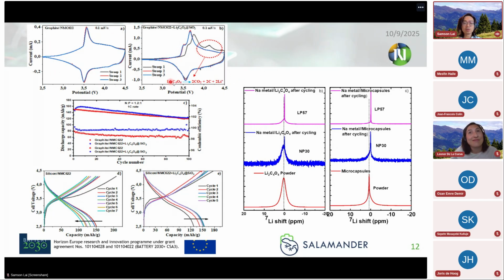And so when you look at the discharge capacity over time, you see that it's much more stable and much better retention over 100 cycles. And we're also really able to confirm that there is lithium oxalate inside these things because we were able to do in situ NMR. And here we did it actually in a sodium metal system so that you didn't get confusing lithium signals from the other parts of the battery.